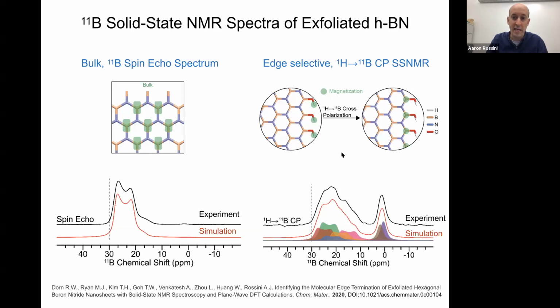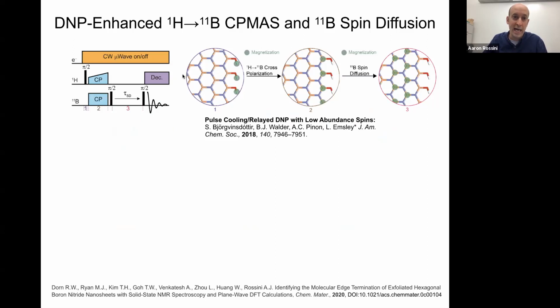Now, one important thing here is if we're looking at these edges that make up a very small fraction of the sample, when we do this cross-polarization experiment, we really want to confirm these are the actual edge signals and not just some trace impurity that's in the sample. You could easily imagine, for example, that 0.1% or 1% of your boron nitride that you buy from a commercial supplier might be contaminated by some oxide or hydroxide impurities. So the way that we can check that is with a DNP enhanced boron spin diffusion experiment.